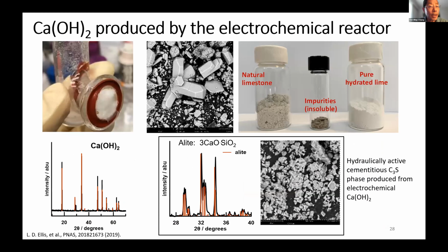It turns out that if you use this to produce calcium hydroxide, which is what you see on the left-hand side here, that calcium hydroxide can then be reacted with silica to produce a compound, a tricalcium silicate known as alite. Okay? And this is the desired phase in Portland cement. And I'll say just a little bit more about that in a second. Okay? So here's a process where at the upper right, you see that you can take natural limestone and produce a pure hydrated lime for cement production.